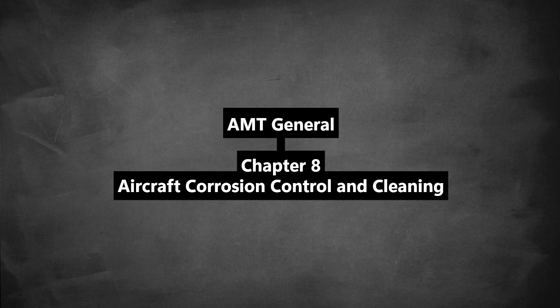Powdered pumice, impregnated cotton wadding for polishing, aluminum metal polish for unpainted alclad only, aluminum wool, less preferred now than nylon pads, rubbing compound for light oxidation, abrasive papers. Use aluminum oxide, 300 grit or finer. Avoid silicon carbide, carborundum, grains embed. Absolutely avoid emery paper or crocus cloth on aluminum or magnesium, embedded iron oxide causes corrosion.